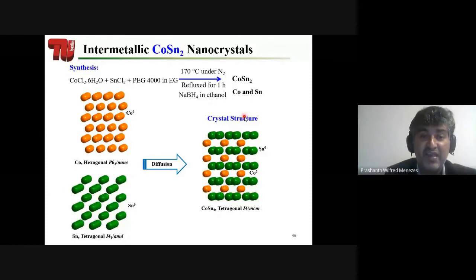How do we synthesize it? We synthesize it in a very simple way. You take cobalt precursor and tin precursor, and if you use such a refluxing condition, we use this diffusion mechanism where the tin slowly diffuses into the cobalt sites, and you form such a nice structure which is tetragonal.